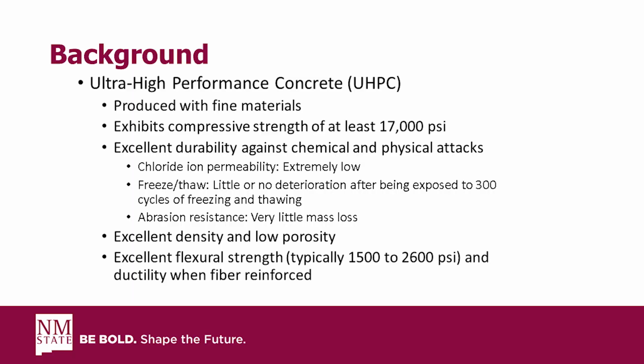So background for ultra-high performance concrete, or UHPC, as I'll be referring to it. UHPC is produced with fine materials, with the coarsest material being a fine sand that's passed through a number 4 sieve. It exhibits compressive strengths of at least 17,000 psi, has excellent durability against chemical and physical attacks. When tested for chloride ion permeability, it showed extremely low permeability, has little or no deterioration when exposed to 300 cycles of freezing and thawing, and showed very little mass loss when tested for abrasion resistance. And UHPC has excellent density and low porosity, excellent flexural strength, typically around 1,500 to 2,600 psi, and is ductile when fiber reinforced.